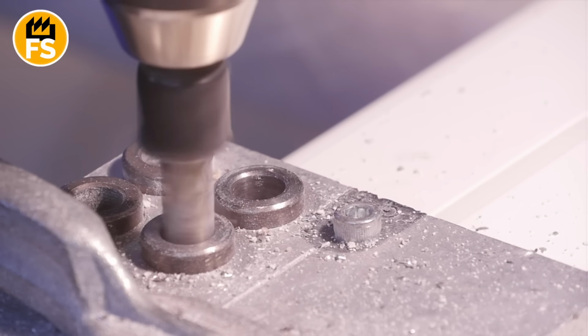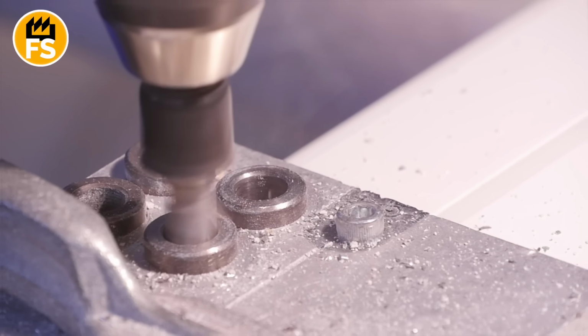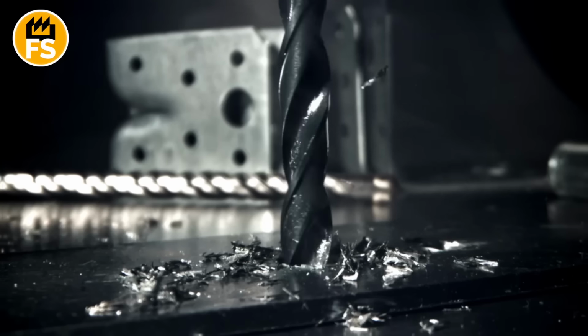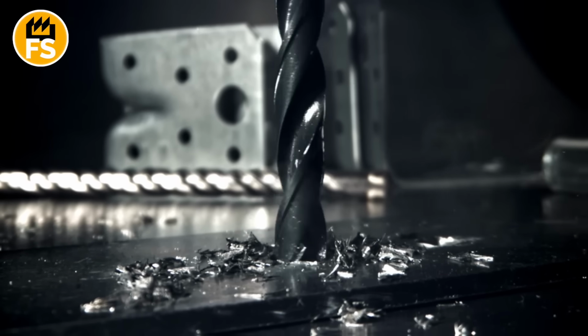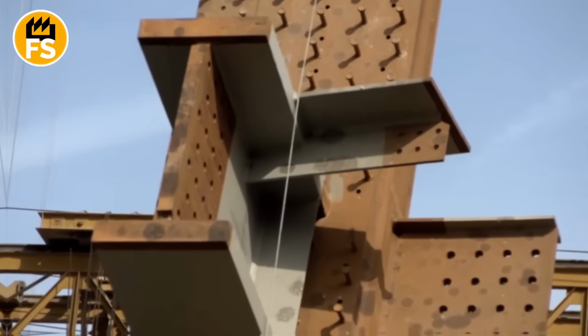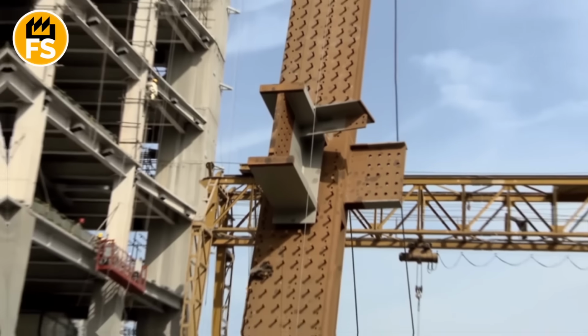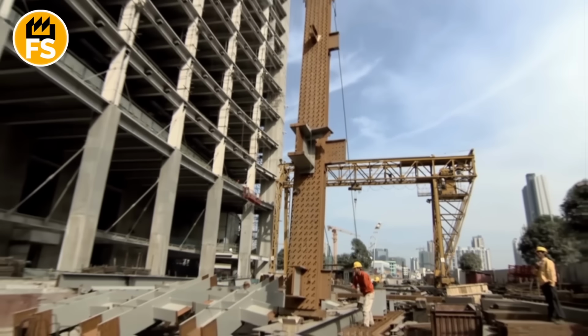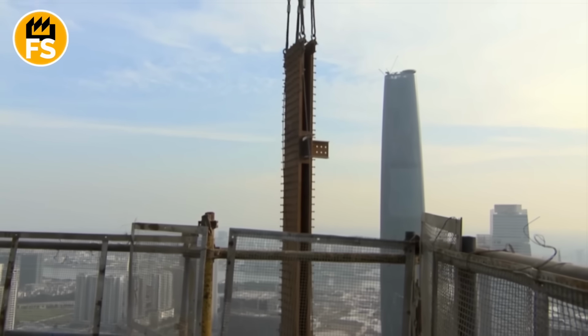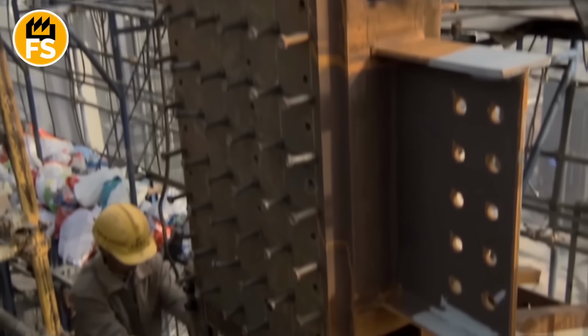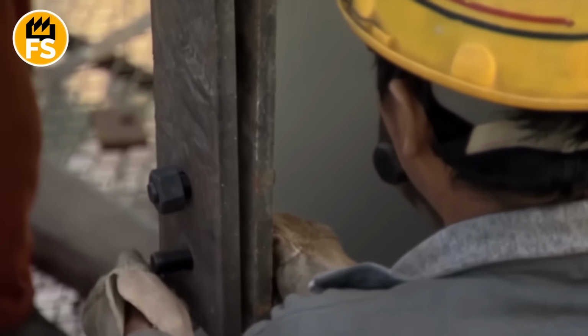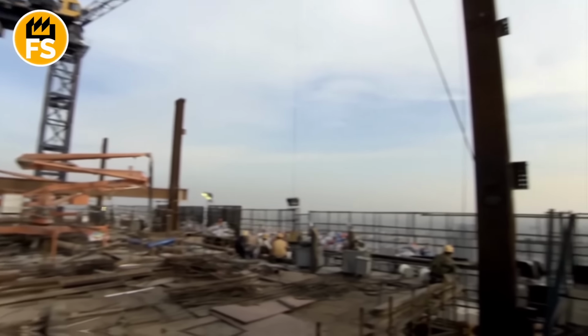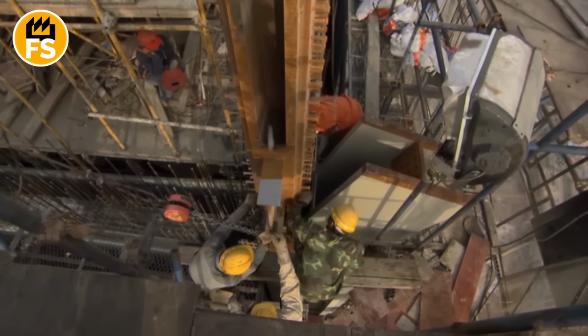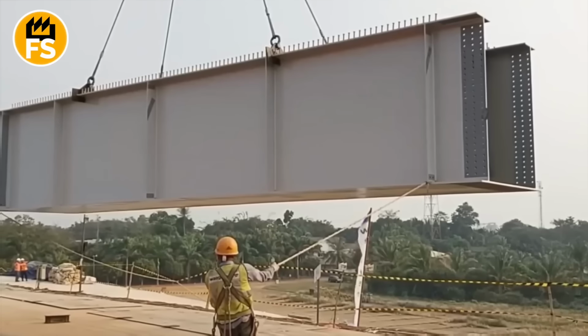And these hole locations are programmed into computer-controlled drilling machines that can position a drill bit accurately within 1/16 of an inch. Some of the main roof beams have over 200 holes drilled into them, and each hole has to be exactly the right diameter and positioned exactly right, because when you're connecting beams that are holding up 31,000 tons, even a small misalignment creates dangerous stress concentrations.